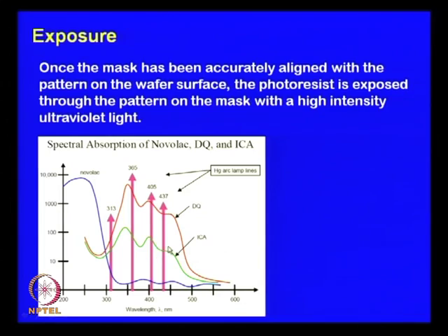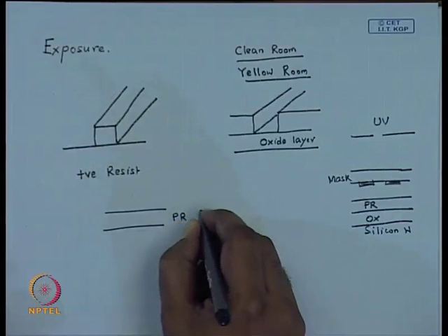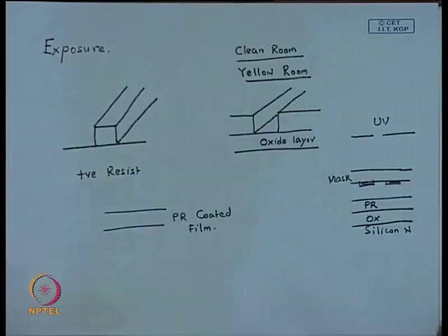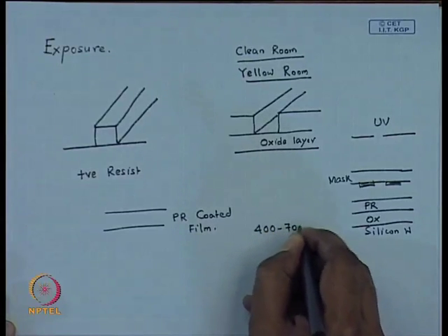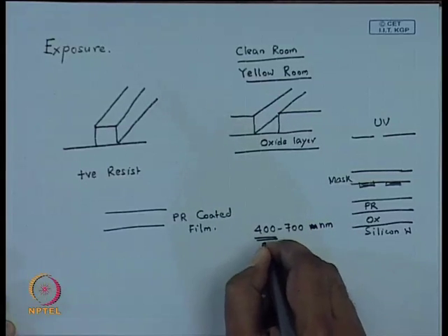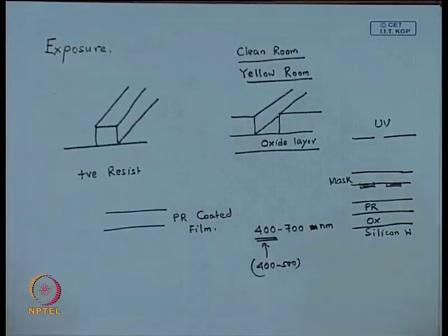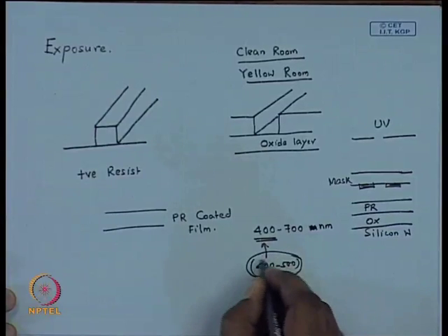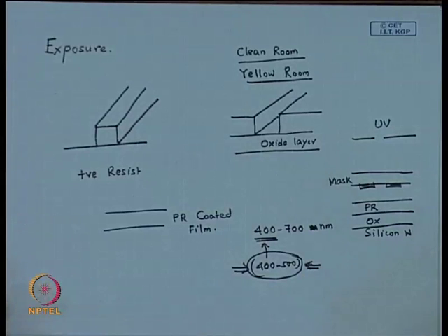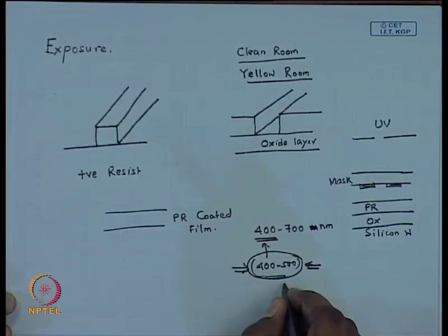Now this is interesting. Suppose you have a photoresist coated film and you handle it in a normal room where your incandescent lamp or a tube light is on. This is white light, you have all the wavelengths between 400 and 700 nanometer. The wavelengths between 400 to 500 start reacting, there is some bit of photochemical reaction within the photoresist layer because of the wavelengths present in white light. You would like to artificially create an environment, because you can't work in complete darkness, where these wavelengths are present in as minimum quantity as possible.